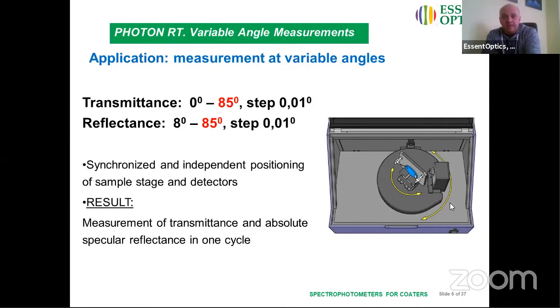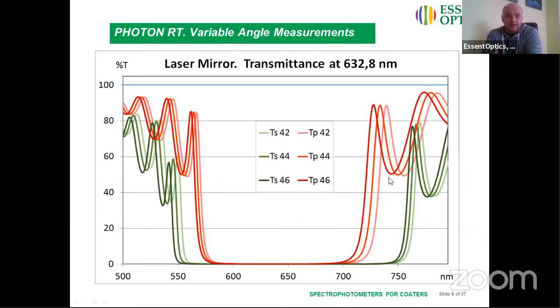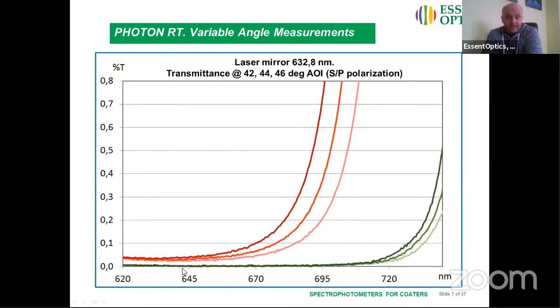Currently, our latest capabilities cover the range of angles of incidence from 0 to 85 degrees without any attachments. You can see an example of laser mirror, and the customer asked us to measure this mirror from 42 to 46 degrees for transmission. And these are the actual values we were able to measure, and the actual noise in the system we were able to get during these measurements.